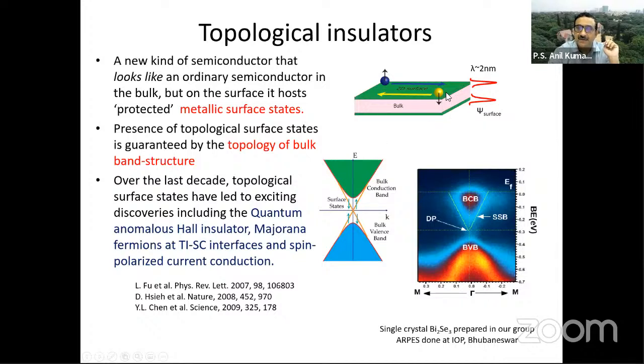Not only that, if you look at the 2D surface state on the surface, you see that the electrons with a particular spin direction move only in one direction because of this peculiar band structure. So if this electron is moving towards the right, and unless it encounters a magnetic impurity, it cannot scatter back, because if it has to scatter back, the spin should be changed. For spin angular momentum to change, you generally need a magnetic impurity. So unless there are magnetic impurities in the system, you can get a very good spin polarized electron source. My interest in this kind of system is due to the possibility of getting a spin polarized electron source here. But these systems are very, very exotic.